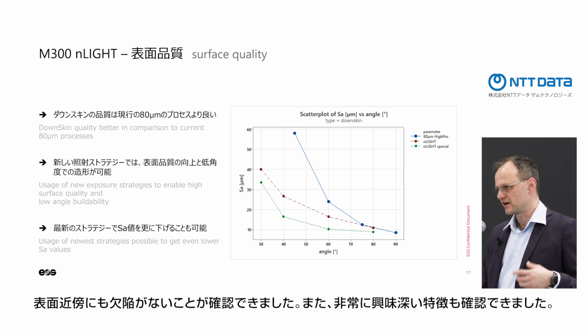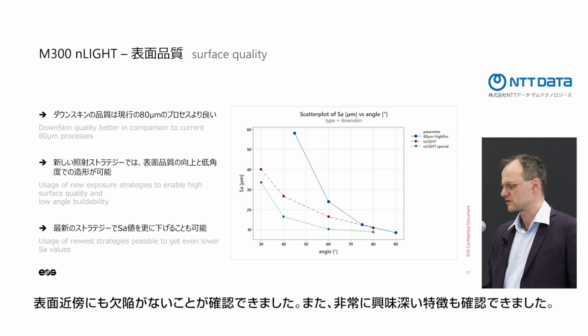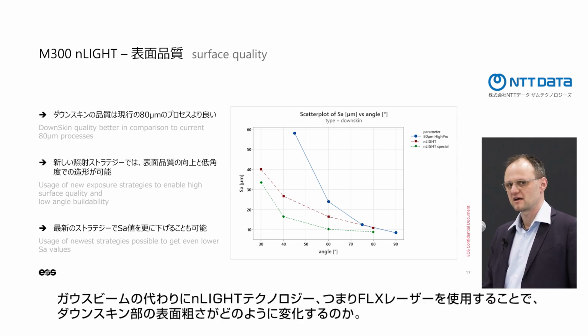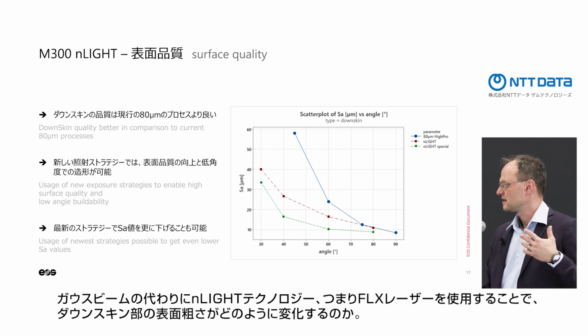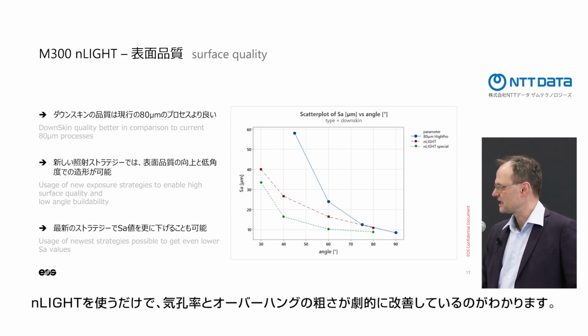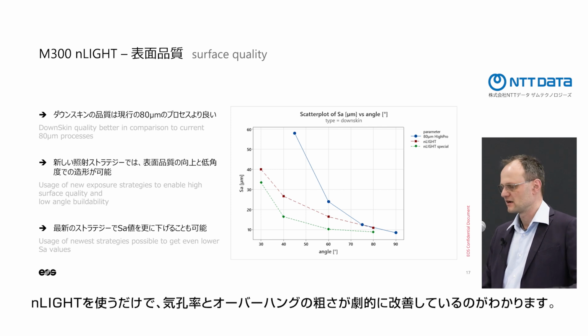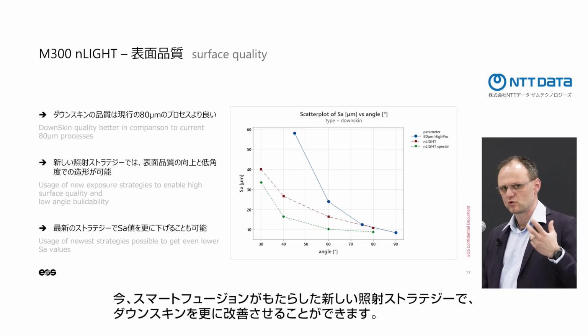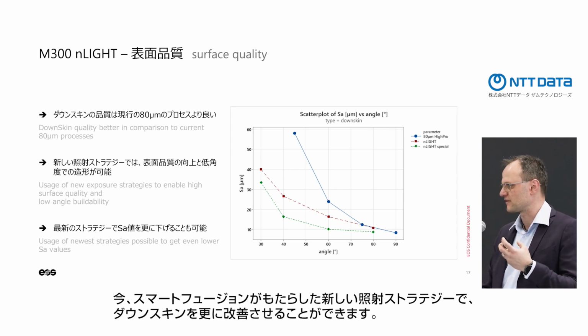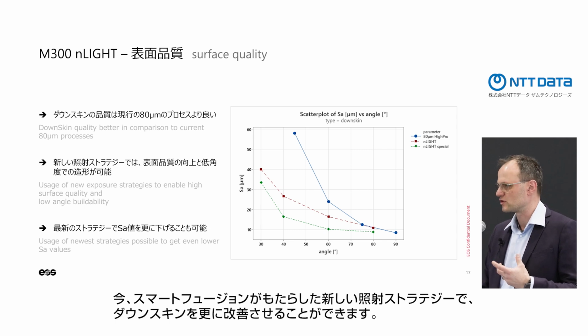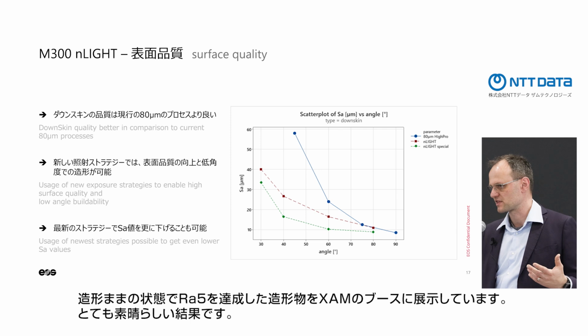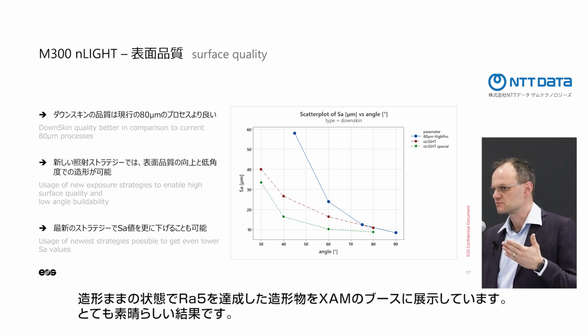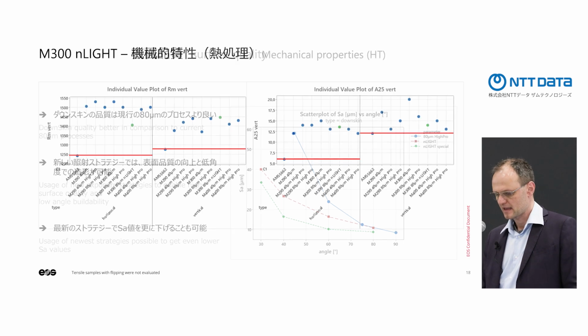We've also checked, which is a very interesting feature of that technology, the effect on the natural downskin roughness of using the N-Light technology, the FLX lasers, instead of the Gauss beam. And you can see that directly out of the box, using the N-Light, the porosity and the roughness of overhangs are getting down quite dramatically. Now, with new exposure strategies that we have learned from Smart Fusion to really have advanced downskin, we can get this even further down. And if you come to the XAM booth, you can see parts with an as-built surface of Ra 5. So this is really very exciting. So it's great.